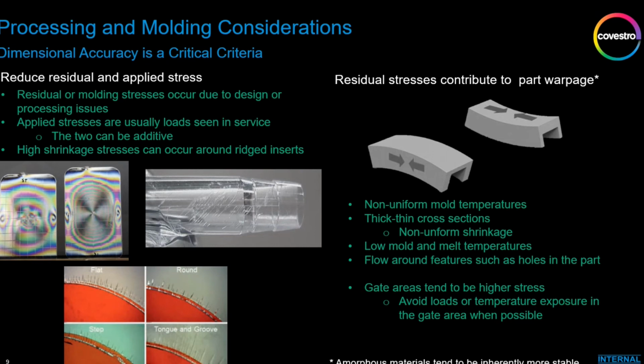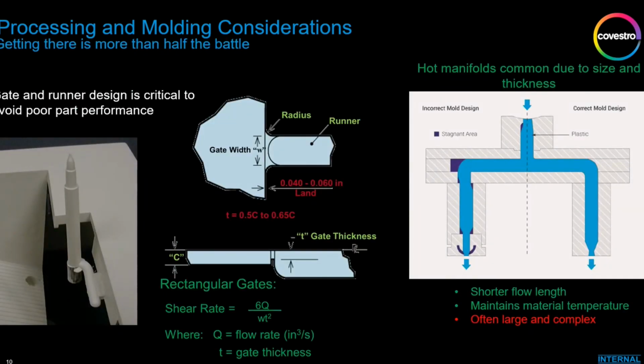Residual stress can contribute to warpage. If you have a residual stress in the part, you heat the part back up a little bit, it wants to go back to its natural state. So if it's got warpage in it and you heat the part up, it's going to deform. Again, for battery applications, that's really not acceptable. The parts need to be consistent, especially for the assembly processing, and then of course in service.